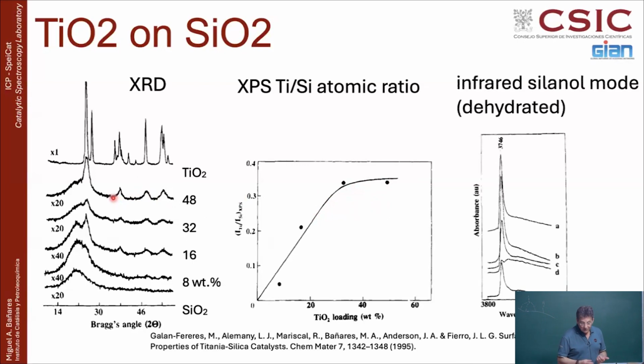Now, where does this titania bind to? The titania is binding to the support, to the hydroxyl groups. So when you are adding titanium to this catalyst, what is happening is that you have hydroxyls from the silica, and you start adding titanium. So the infrared spectrum of this catalyst will tell you that there is very little hydroxyl group left. So here, D is this one. You are at the monolayer coverage.